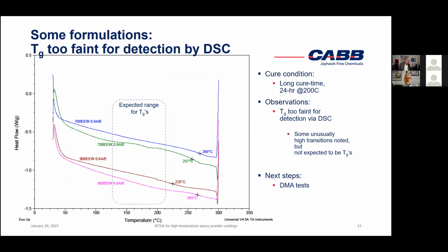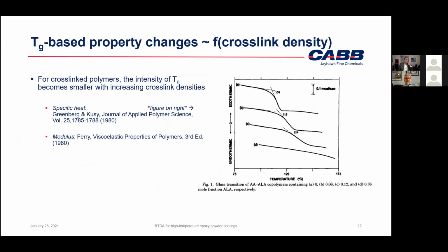But before we go to the DMA, I just want to show that this issue of TG suppression is well known in the industry and well known in academia. So this is an example of some acrylic acid polymer where it shows that in a DSC, the TG will keep going higher and higher as you increase the level of cross-linker in the polymer. And the TG also becomes more and more suppressed, to the point that at this fourth level here, the TG cannot even be discerned by DSC. Same thing that we noticed.